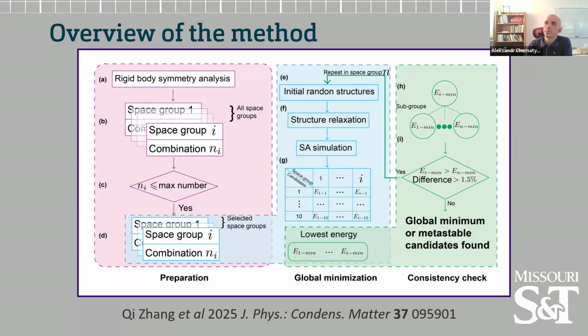That will generate an initial random structure in this place. The structure will be relaxed, just as I described, and launched into a simulated annealing simulation, in which case it's going to be a Monte Carlo simulation in which we're going to use Metropolis acceptance as a criterion to accept or not accept a new structure. We will periodically do relaxation to ensure that the rigid blocks do not fall apart and everything checks out, and that will produce the candidate structures, which we then will record and keep track of what the 10 lowest structures in a given run are. That will be followed by post-processing, in which case we're going to look at what are the possible candidate structures, what is the relationship between them in terms of group-subgroup relationship, and looking at the phonons of the most promising structures. So this is kind of the overall setup.